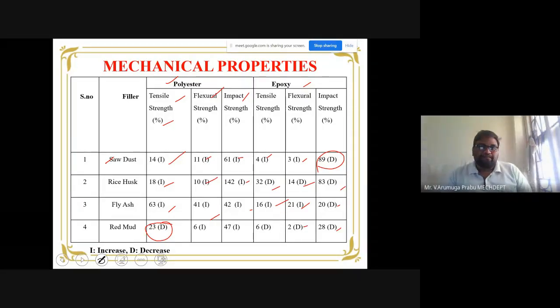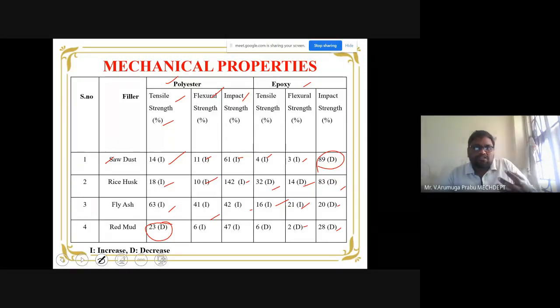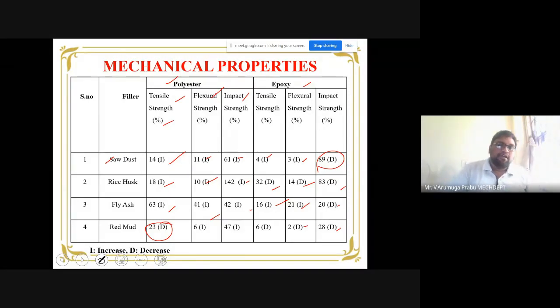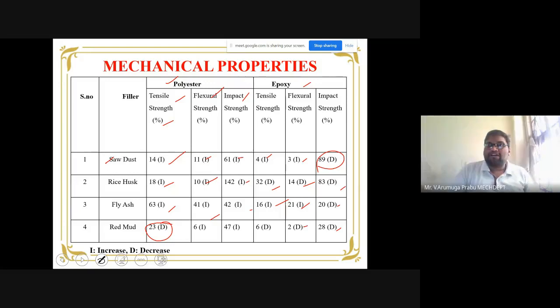On the other hand, the polyester shows an increase in all the strengths, and you see in the fly ash, rice husk, sawdust, all these three wastes show an increase in weight percentage in all the three cases, that is tensile, flexural, as well as impact. Only in the case of red mud, we noticed that the non-uniform distribution of these fillers will produce a decrease in the tensile strength, because the fillers accommodate to one particular base.